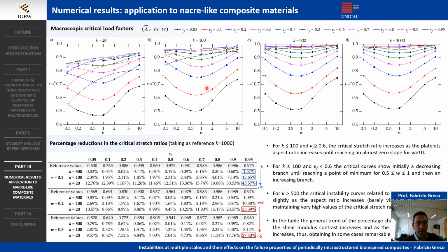In addition, for the cases with the large shear modulus contrast, K larger than 500, the critical instability curves related to large values of platelet volume fraction increase only slightly as the aspect ratio increases, maintaining very high values for the critical stretch ratios. By taking the critical stretch ratio obtained with a shear modulus contrast K equal to 1000 as a reference, the percentage decreases in the critical stretch ratio have been summarized in this table for composites with varying shear modulus contrast, platelet volume fraction, and platelet aspect ratio.